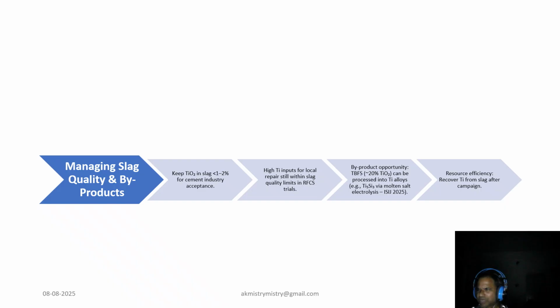So now coming to one more consideration, slag quality. If titanium in slag exceeds 1 to 2%, cement producers may reject it, because our major consumers are the cement producers. So we have to be very concerned about the presence of Ti. But the good news is, even in aggressive injection trials, TiO₂ level in slag stayed below this limit. Also, there is a byproduct opportunity. Titanium bearing blast furnace slag, or TBFS, contains around 20% TiO₂. Recent work shows it can be processed into high value Ti₅Si₃ alloy using molten salt electrolysis, turning a waste product into something valuable.